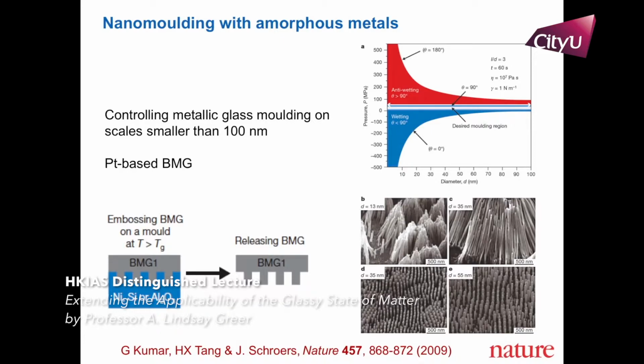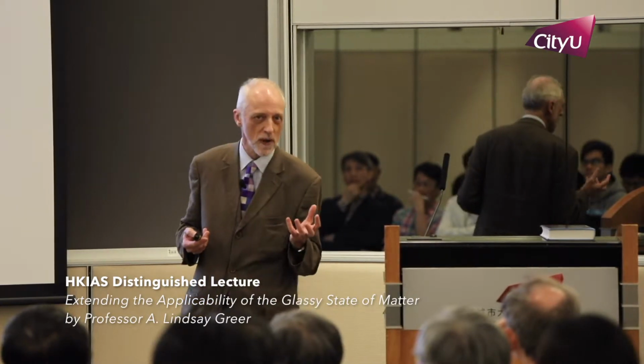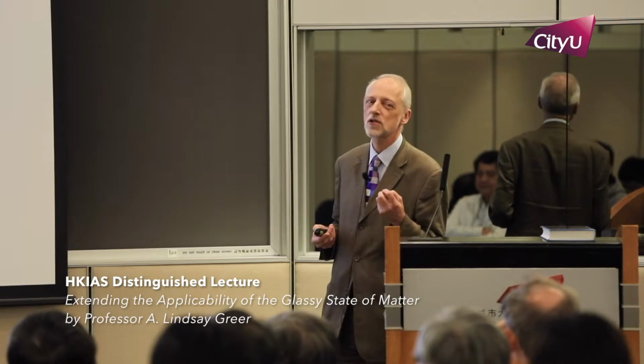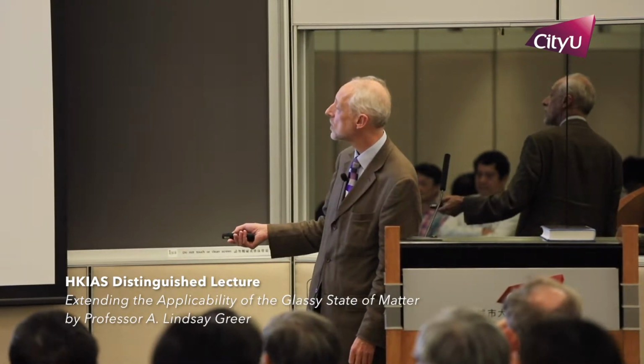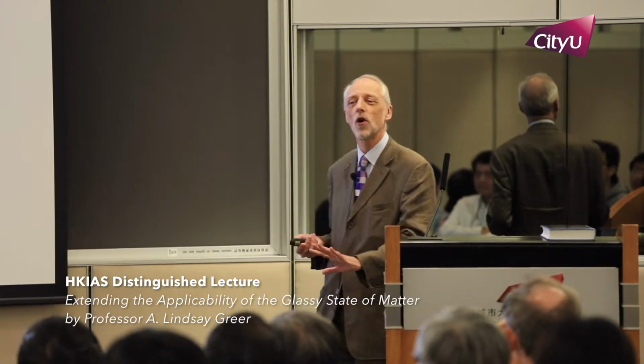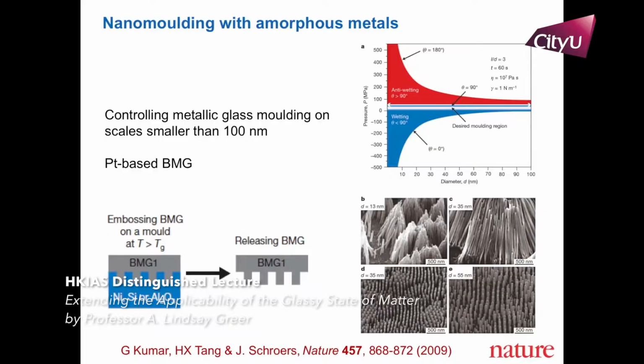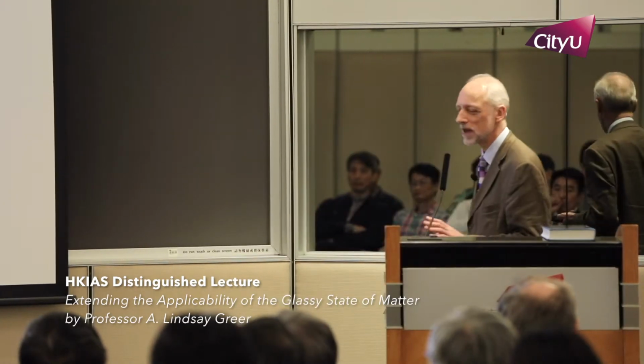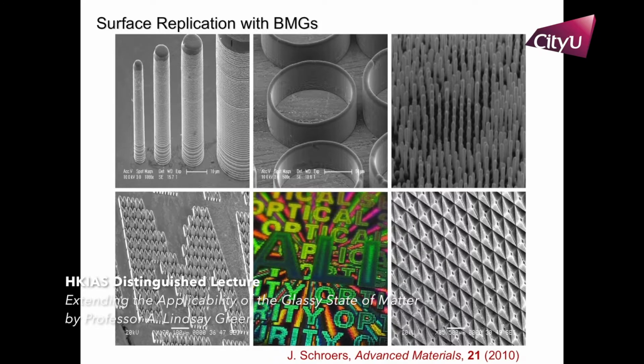More interesting, really, is probably the fact that the metal system as a glass does not have a microstructure inside like your usual metal, so you don't have grain boundaries. And because you have no internal structures of that kind, you can impose a pattern on the surface that is what you wish to impose, not what the material wishes to impose. These show remarkable results where you can extrude the glass into little holes in the ceramic template, down here, to a diameter of these rods that would go down into these holes. The diameter is a mere 13 nanometers. Quite remarkable capability for capturing the shape of the surface, and of course easily able to give you optical patterns which you would use in various ways.